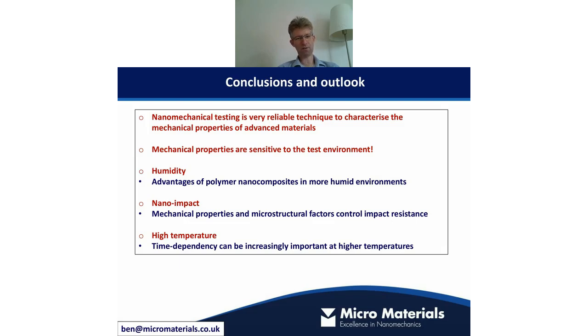The main part of this talk was really to emphasize that material mechanical properties are sensitive to the test environment. So I gave three examples. Humidity, where we showed that the advantages of putting clay into these polymer nanocomposites was much more beneficial in high humidity environments. In impact testing, I showed you how it was really a combination of the mechanical properties and the microstructural factors that control impact resistance in these advanced coating systems. And in high temperature testing, I showed how time-dependent deformation was increasingly important at higher temperatures. Okay, thank you very much.